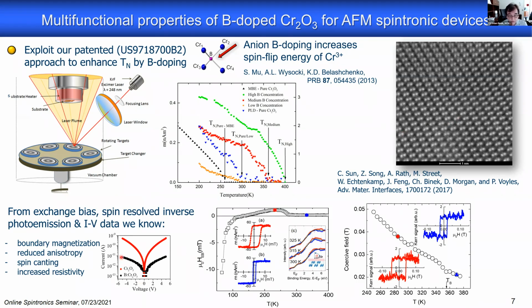And we also learned from IV curves, from transport measurement, that the boron doping had a surprisingly positive effect on the leakage. It reduced it rather than increased it. So you see here the currents for applied voltages in the IV curves are lower than they are in the pure chromia. So that kind of forced us to a new path.